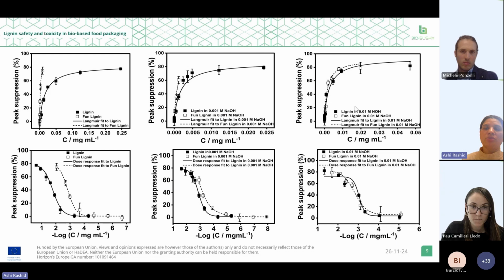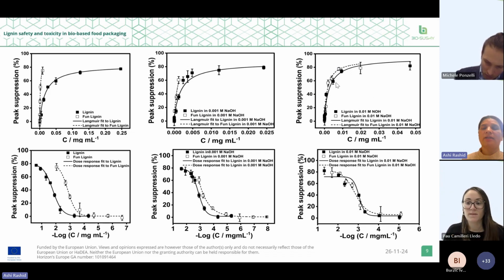Further increasing the amount of sodium hydroxide, there is no significant difference in the interaction of functionalized and unfunctionalized lignin. So the interactions in the unfunctionalized lignin, because of the depolymerized product, reach almost the same extent as the silane protected lignin. A similar kind of data can also be seen in the dose response plots.